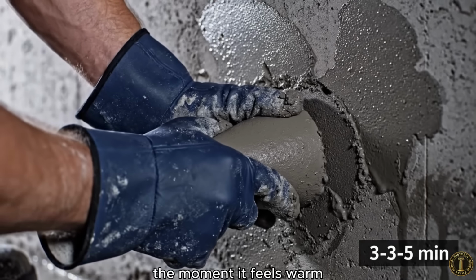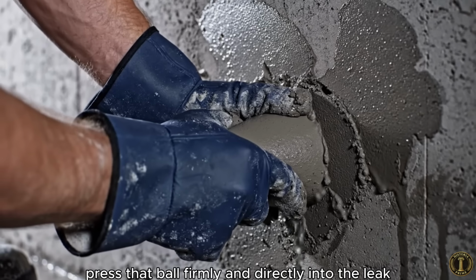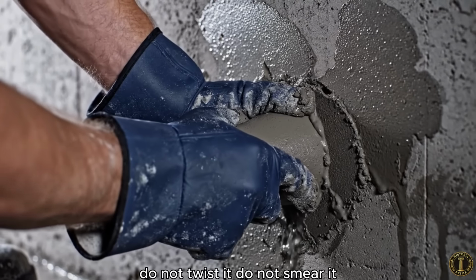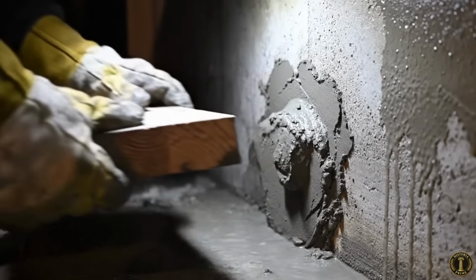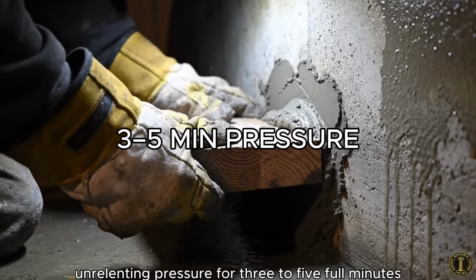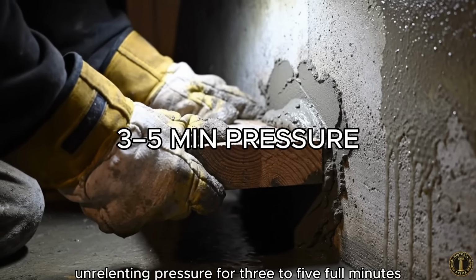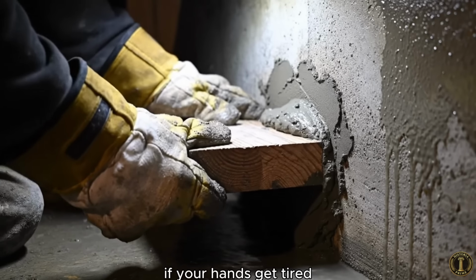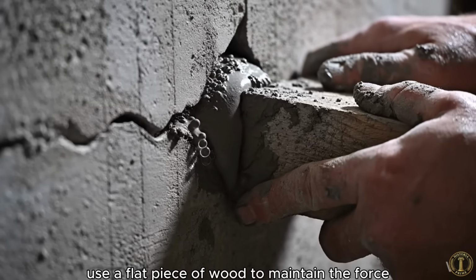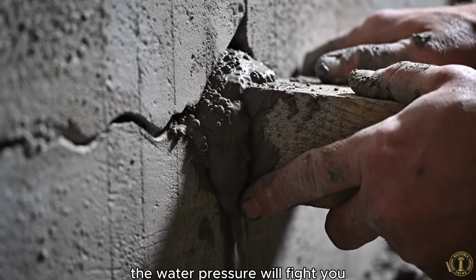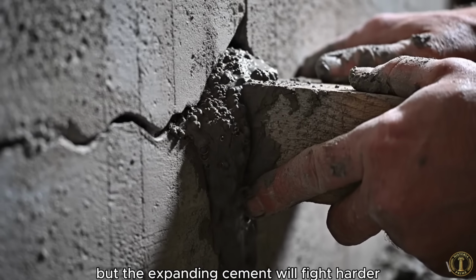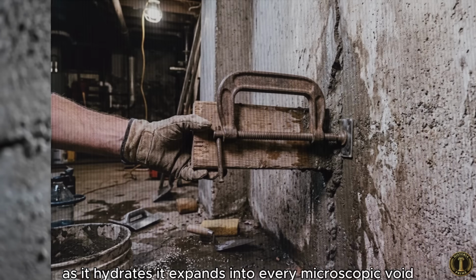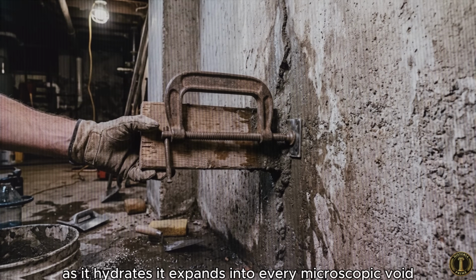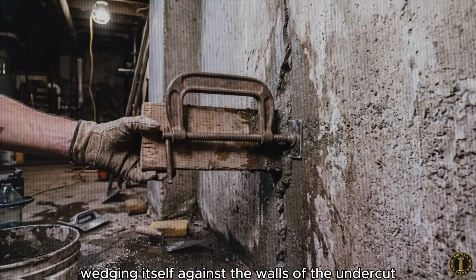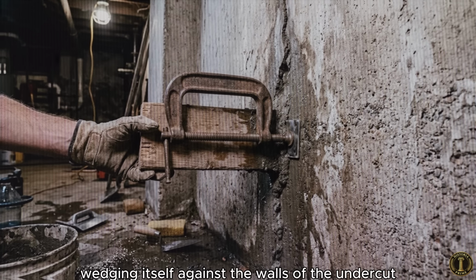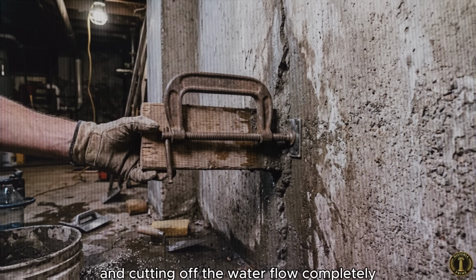The moment it feels warm, press that ball firmly and directly into the leak. Do not twist it, do not smear it. Press with heavy, steady, unrelenting pressure for 3 to 5 full minutes. If your hands get tired, use a flat piece of wood to maintain the force. The water pressure will fight you, but the expanding cement will fight harder. As it hydrates, it expands into every microscopic void, mechanically wedging itself against the walls of the undercut and cutting off the water flow completely.